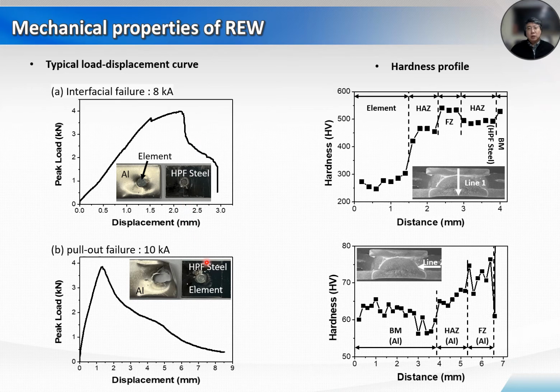When applying a welding current of 8 kiloampere, the increase in fracture load was not quite rapid. Element deformation seems to be the main reason for the load increase and results in interfacial failure between the element and lower steel sheet. This is attributed to the small nugget diameter and the observation of the notch on the cross-section. Cracks propagate and fracture occurs at the interface between element and steel.